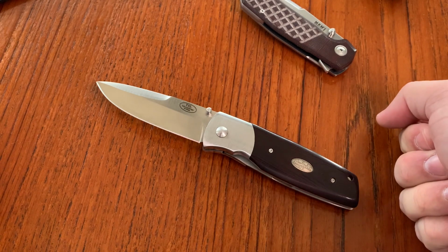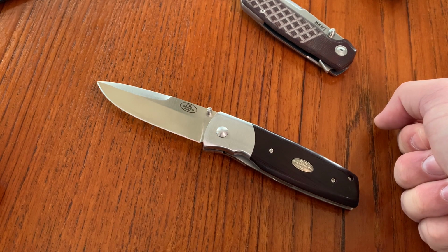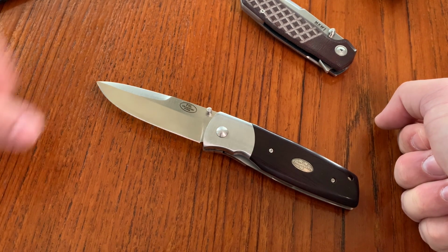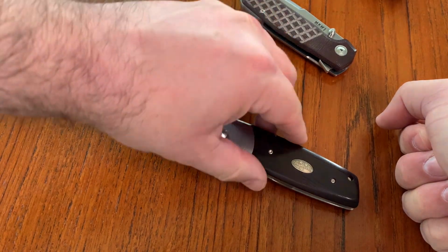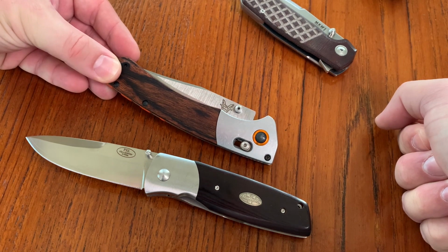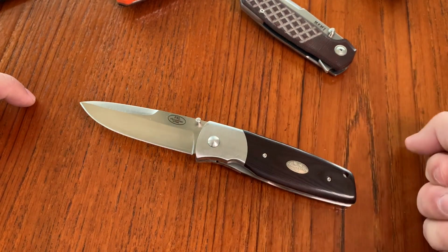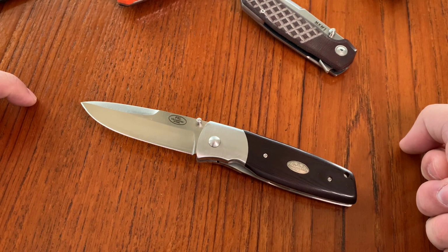One thing about the Super Gold steel, the center layer of this laminate in the 3G, which I mentioned is similar to S30V: it is, but the working hardness for this is higher. An S30V knife, properly heat treated, is going to be in the range of 59 or 60 on the Rockwell hardness scale, whereas the SPG is going to be higher than that. It's going to be 62-ish, which is significant, right?